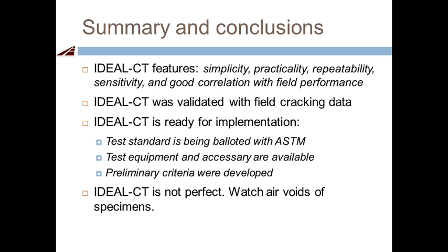Would you propose implementing this test in a specification for mix design only, field QC only, or both? Both. Is it appropriate to test specimens at the actual in-place air voids of the plant mix? For the ALF and Texas work, we got plant mix, reheated it, and compacted to 7% air voids — we did not test field cores.